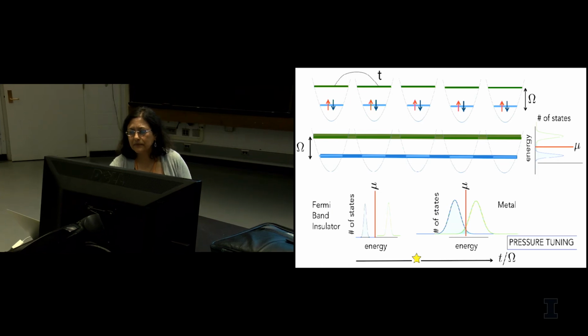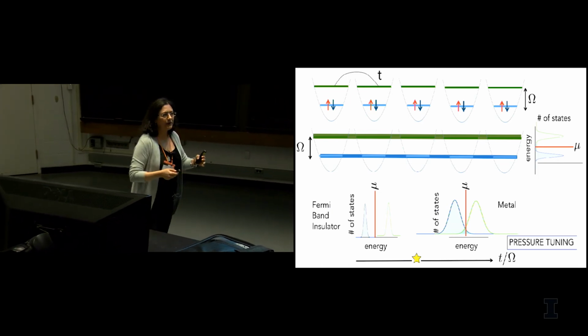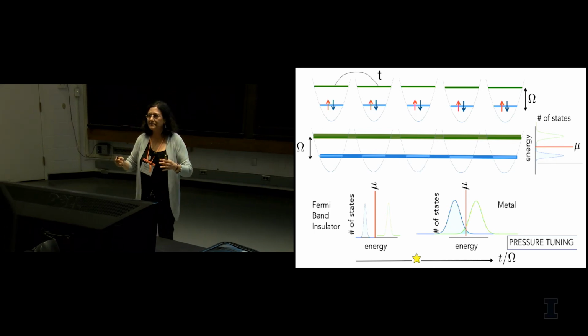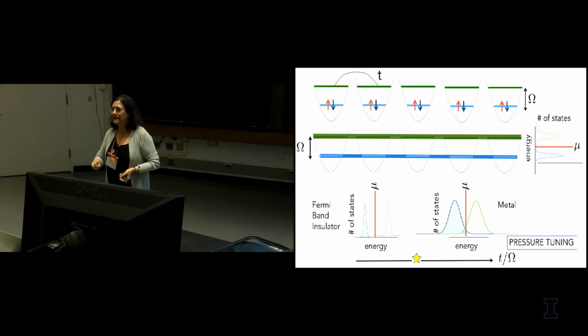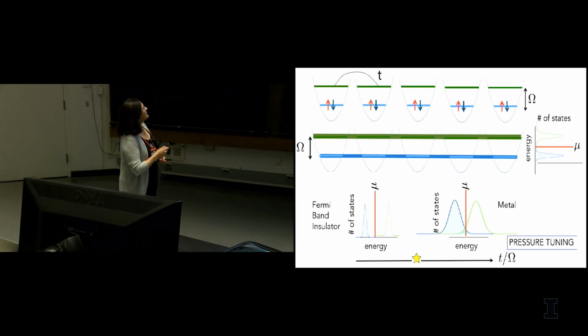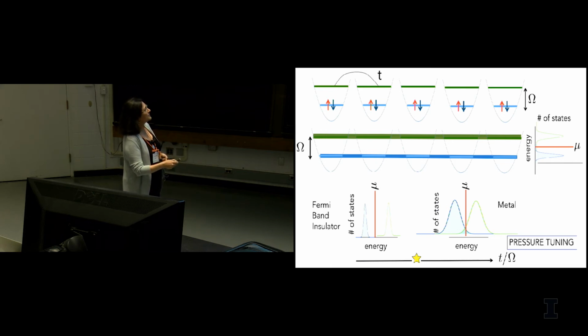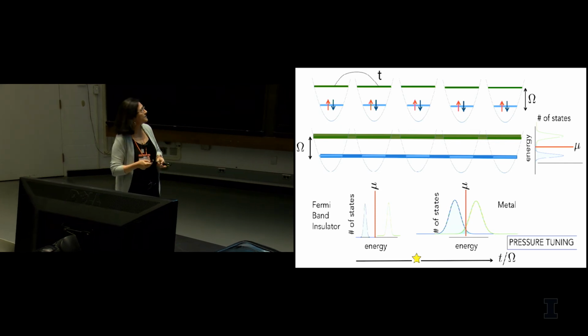Okay, so what we have done are some model calculations on this, and we have some very definite answers. I'm going to just give you the basic idea behind that. Let's say you take a site with 2 orbitals and have 2 electrons, then essentially what you get is a completely filled band. Here I have these 2 orbitals on each site, and I turn on some tunneling that gives me these two bands with 2 density of states in blue and green. If I put 2 electrons per site, that essentially fills up the blue band and gives me a chemical potential in the center. So that would be the typical band insulator.